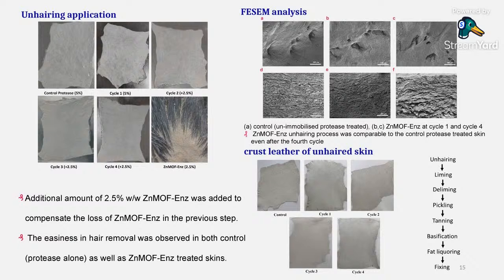Then we did the control protease, because that is our positive control. We took the skin and added 5% of control protease, and we looked at the surface, and the hair is completely removed. And if you look at the bottom portion, the zinc MOF enzyme at 2.5% is not doing that much. So we took 5% loading of enzyme on the zinc MOF, that is the immobilized enzyme. Then we treated the skin at cycle 1. And in cycle 2, we added an extra 2.5%.